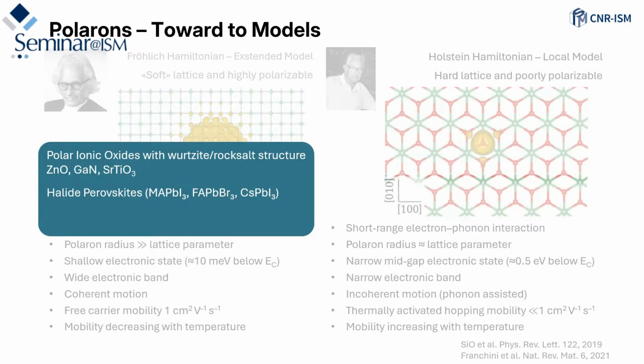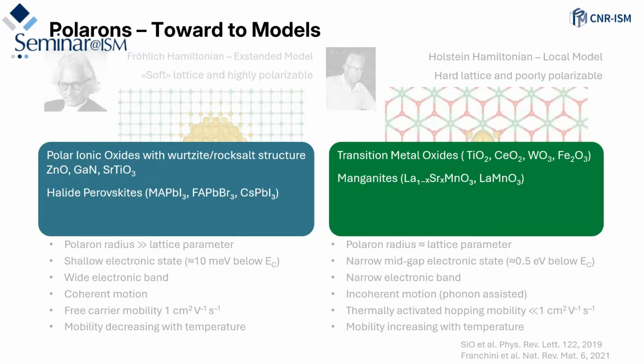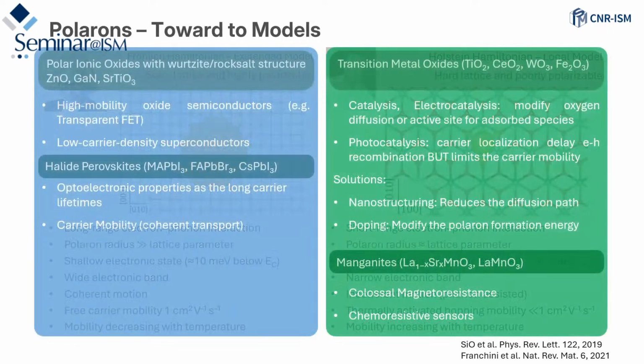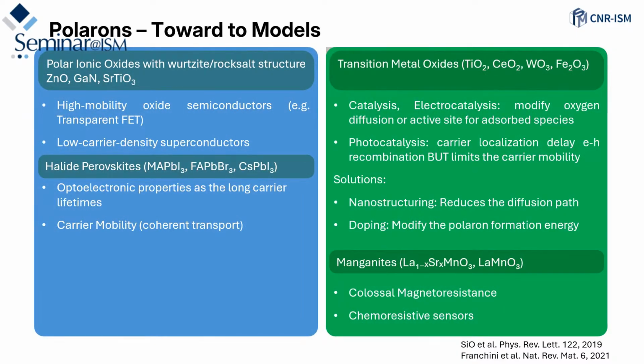Just to mention some materials that are involved with large polarons: polar ionic oxides with wurtzite or rock salt structures, such as strontium titanate, for example, but also lead halide perovskites have this large polaron formation. On the other side, transition metal oxides are quite known to have small polaron formation, and also manganites. Considering the applications or phenomena that are mediated by polarons, we can mention for the polar ionic oxides the high mobility, and for example the halide perovskites, they have very good optoelectronic properties, as the long carrier lifetime could be induced by large polaron formation.